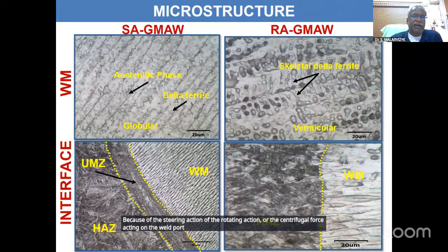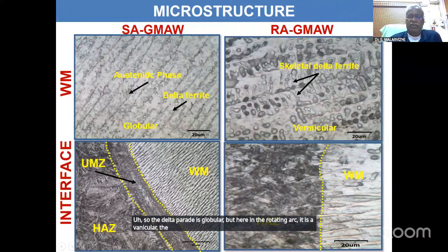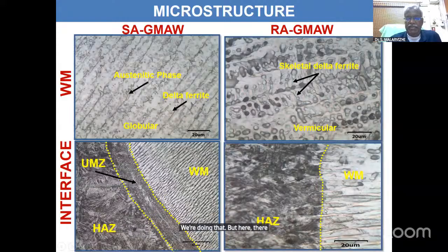In the stationary GMAW, the delta ferrite is globular. But here in the rotating arc, the delta ferrite is formed as vermicular. And similarly, because of the single V groove we are taking, there is an unmixed zone, UM, between the weld metal region and the heat affected zone. But here, there is no unmixed zone between the weld metal and the HAZ because we are using the straight edge or square butt configuration. And this, of course, we can explain.